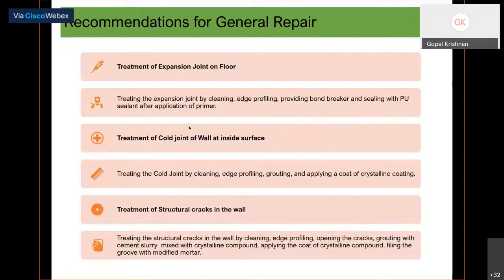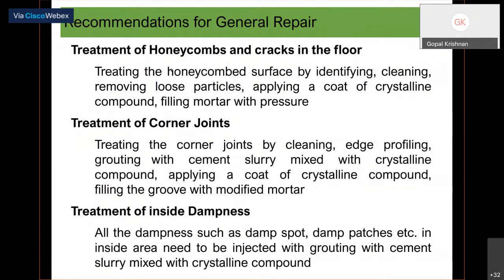So for each point, expansion joint, cold joint, or structural cracks, we told them to repair with a cementitious, crystalline based product, so that it has crystalline growth and blocks the porosity and makes a proper impervious surface, as well as growth in the concrete or the repair product. So we gave, stage wise, what coating is to be given on the internal side, what mortar is to be used for repair, and what coating to use to avoid dampness, moisture or water entering the concrete wall or floor.